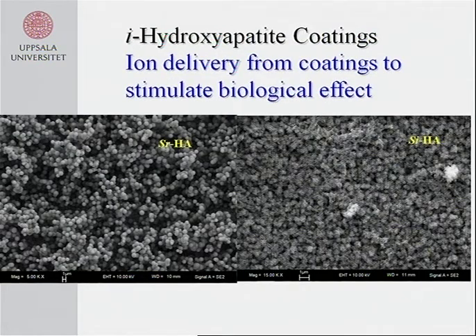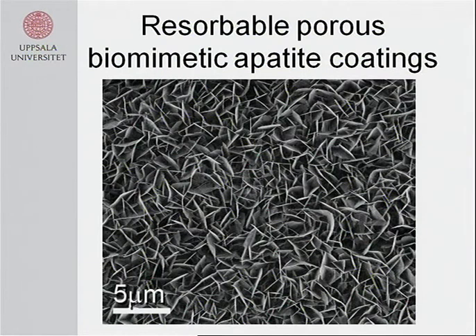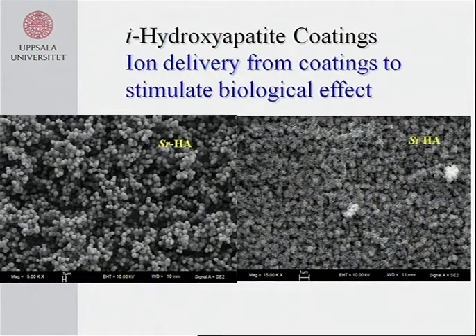A new venue that we entered a couple of years ago is to combine this with ion substituted HA. In this first case, this is a pure hydroxyapatite coating, only calcium, phosphorus type of calcium coating. And in this case, we have produced coatings where you exchange or add some strontium. You could also load this with drugs, and you get a slow release of strontium as well. And strontium is known to be effective for increasing bone strength. So we have measured the release of strontium from the coatings. We see that you have a slow release of that, simultaneously with the release of a drug as well. And in this case, it's a silicon hydroxyapatite.